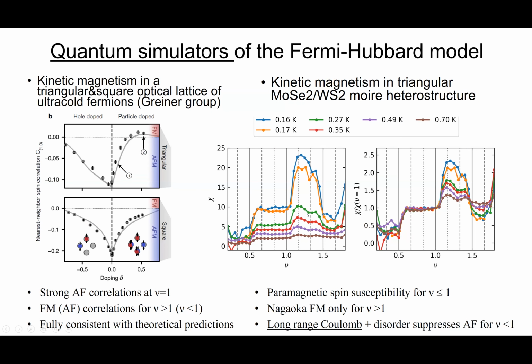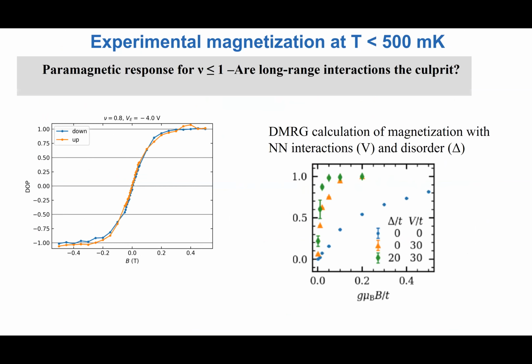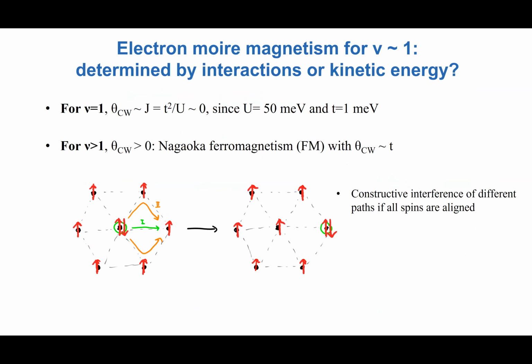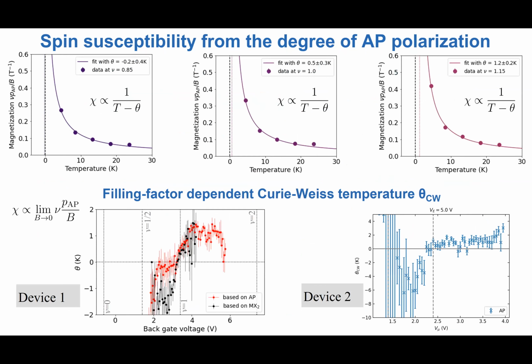So I showed this data. I didn't have time to explain this to you. So this high temperature data that basically got us excited about antiferromagnetic correlations, this one is a pure exciton-induced depolarization. What really woke us up is that we wanted to check how robust this is for light-induced effects, because we've seen light-induced spin depolarization before in monolayers. So this was taken at about 10 nanowatts. We have to decrease the power by more than three orders of magnitude to get rid of this effect. But at the very low filling factors, even picowatts is not happening. But you can clearly see that low power fixes it more.